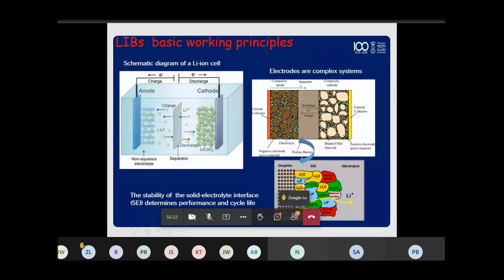As I said, the SEI is essential, so without it the system will not work. And its stability, of course, is essential. If you have an unstable SEI, the system will break, and the cycle life will be very low. So this is the solid electrolyte interface. The stability of the solid electrolyte interface determines the performance of the cell itself, but particularly the cycle life.